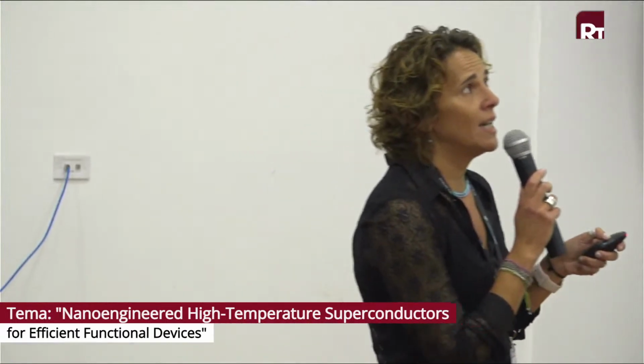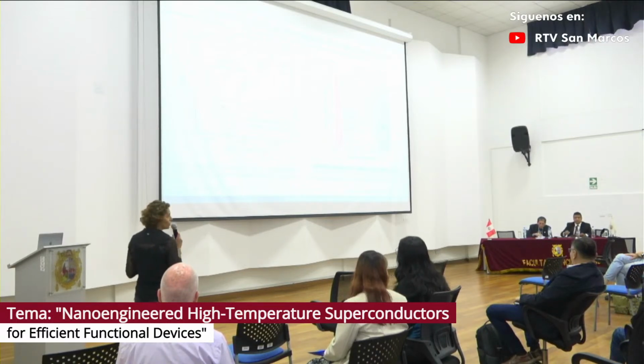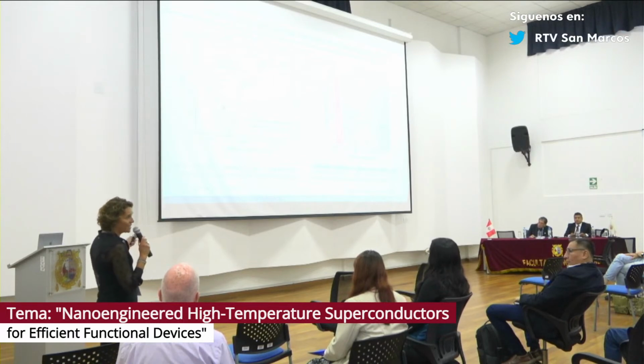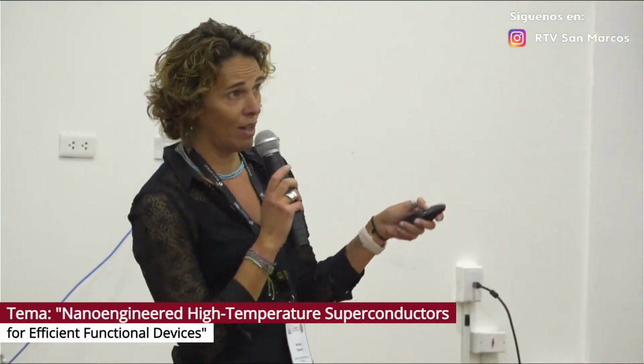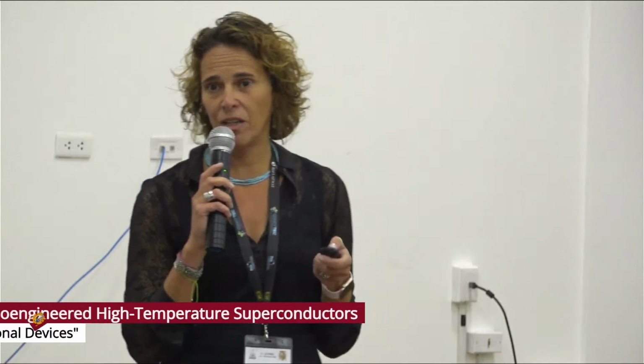Thank you. So this is just a way to see that you can modulate the TC and also the carrier density, and it more or less follows this trend. But exactly, this is carrier density, and in this case, this is oxygen doping. And oxygen doping is related to the carrier density, but it's not the carrier density itself. So we have not evaluated directly the carrier density, and we can have big changes in here. But it's just to show that we can follow this trend, and this needs to be more analyzed if you want to know exactly where you are in the system.